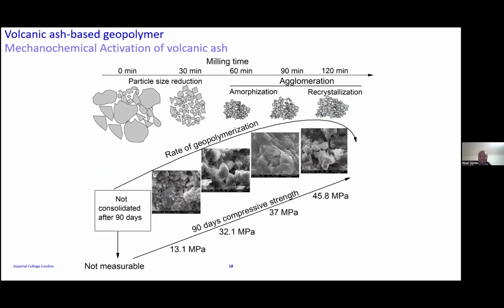Apart from blended cement, I've also used the same volcanic ash to make a geopolymer cement, which is produced from the process that I showed in one of the previous slides. This slide summarizes the changes in the particle size of the volcanic ash and the effect on the mechanical property. This was really fantastic because, as you can see at the beginning, the volcanic ash that I used to make this geopolymer cement was not working at all. By mixing it with the alkaline solution, as I presented previously, I could not get a material that hardened. Even after 90 days, the material was still soft, which means that volcanic ash was not suitable at all to make geopolymer cement.